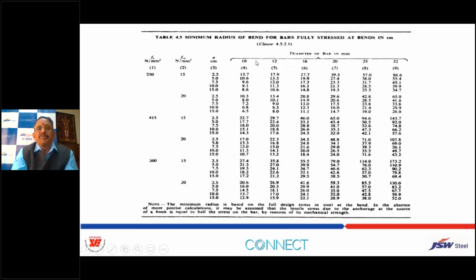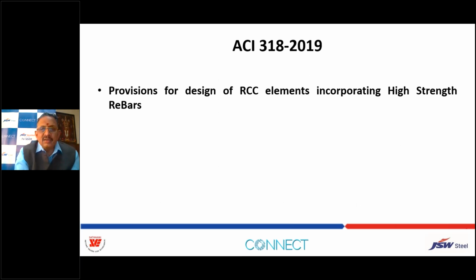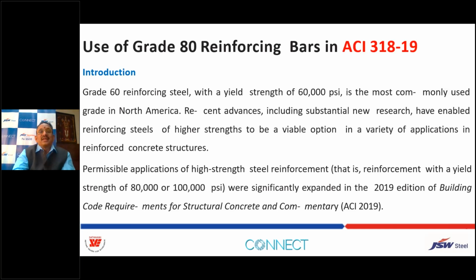So next is the minimum radius of bends that are given. They have to be maintained for all the grades of bars, and it is given only up to 500, and now it needs to be modified beyond this. And that's why I said let us look at the ACI 318-2019. This is the latest code which has incorporated high strength rebars. So use of grade 80, that is beyond 600. 80 is actually based on PSI, 80,000 PSI, and so it is equivalent to 600 plus. And then we have reinforcing steel grade 60, which is 60,000 PSI, the commonly used grade in North America at present. And ACI now talks up to 100,000 PSI, which can be up to 700.